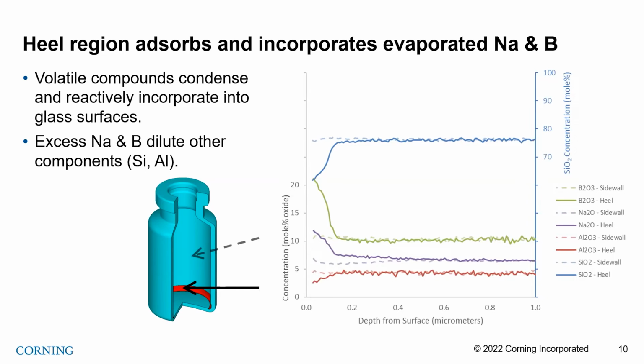So controlling the glass surface chemistry on this scale of hundreds of nanometers is necessary in order to prevent those defects from occurring. So Corning did this through creation of a new glass composition that didn't include boron. And by omitting boron from the formulation, we were able to stop this evaporation and condensation reaction from occurring.